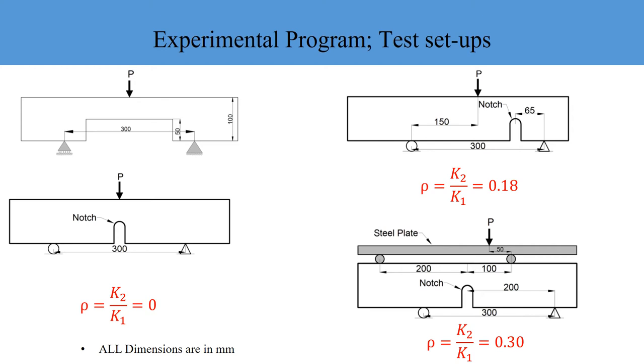This slide shows the test setups used to generate different levels of loading mixity. The level of loading mixity is quantified by rho, which is the ratio of mode 2 stress intensity factor over mode 1 stress intensity factor, determined by replacing all notches with ideal zero-tip cracks. For all specimens, digital image correlation was carried out using a high-speed camera to calculate displacement around the notch surface at any orientation. Mode 1 tests were carried under classic three-point bending, one mixed mode level also under three-point bending, and the final loading mixity was generated under anti-symmetric four-point bending.